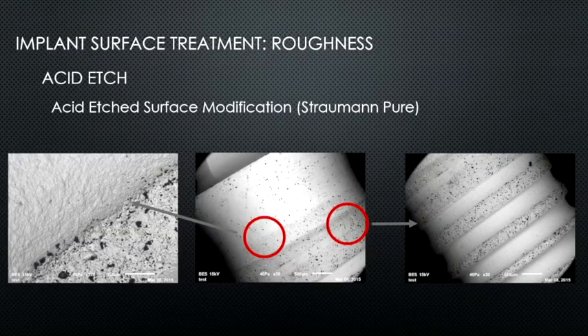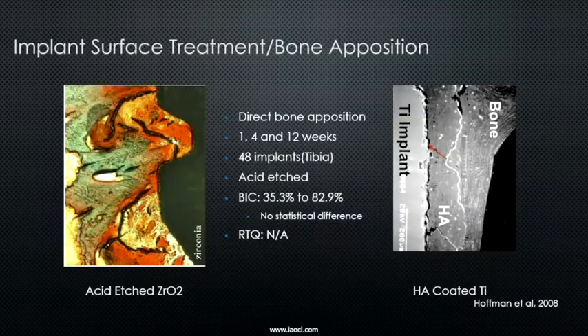Okay, you see the difference between here and there. And that's a slide that really illustrates what happens. On a ceramic implant, you have direct bone to implant apposition. On a coated implant, you have the titanium inside, the HA in between, and then the bone outside. When the HA starts to break down, that's when you have a separation, and then you lose your implant also. And when it breaks down, the metal gets exposed, the corrosion starts, and you have a problem.